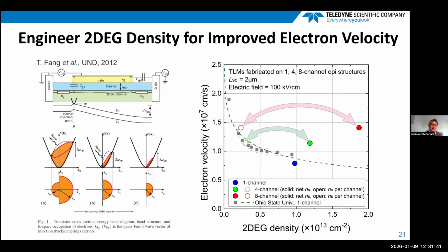He's now at Cornell. With increasing the 2DEG density in a single channel, the phonon emission rate increases, resulting in the reduction of electron velocity at high electric field. So by having a smaller 2DEG density in each channel, the saturated electron velocity can be increased. So in the multi-channel configuration, we can minimize the 2DEG density in each channel, but we can stack them up to have a high net 2DEG density.